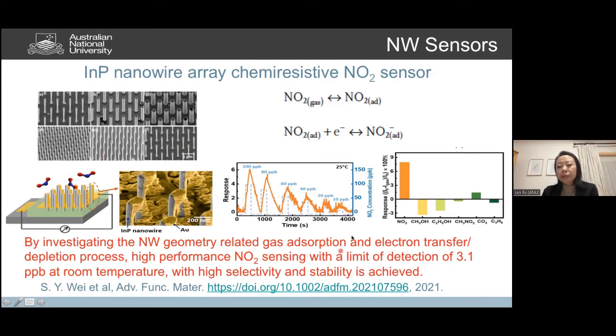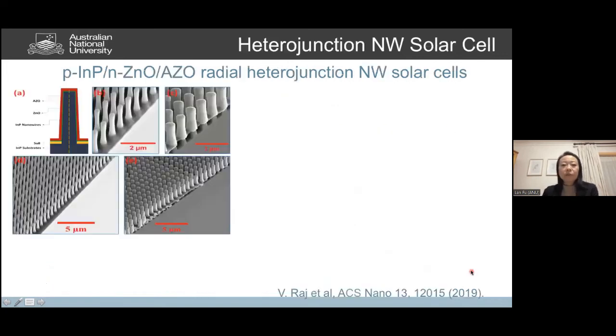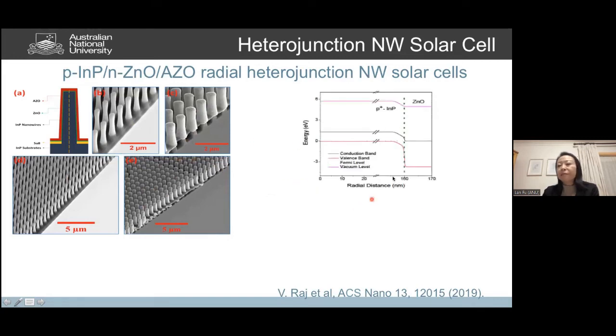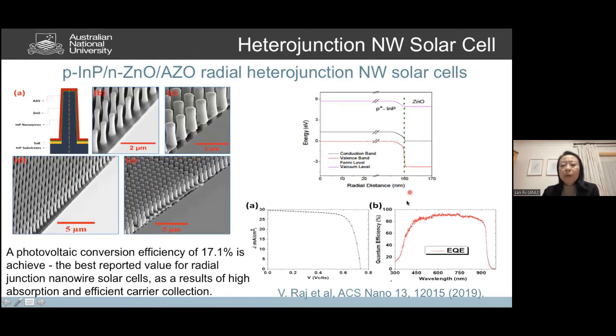And we have recently also shown that by implementing a PN junction inside the indium phosphide nanowire array, we're able to do self-powered sensing, and we're going to submit that work very soon. Another work we have done using top-down indium phosphide is making a radial heterojunction by depositing zinc oxide on top of it. Because zinc oxide and indium phosphide have a very nice type 2 band alignment, we're able to create very nice solar cell behavior, because the type 2 alignment blocks some carrier diffusion and enhances performance.